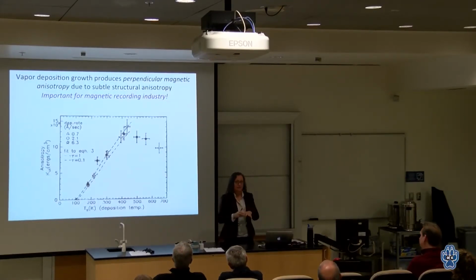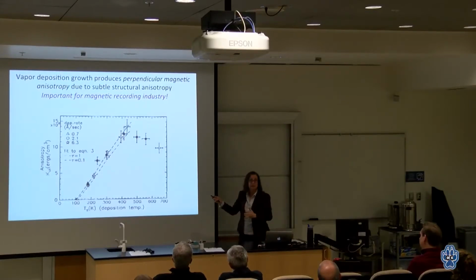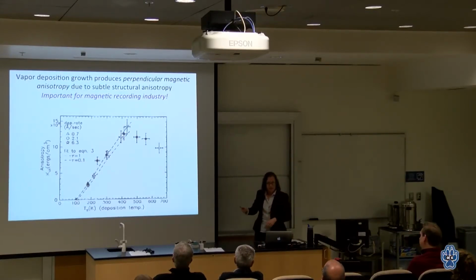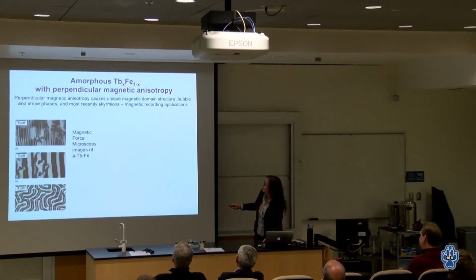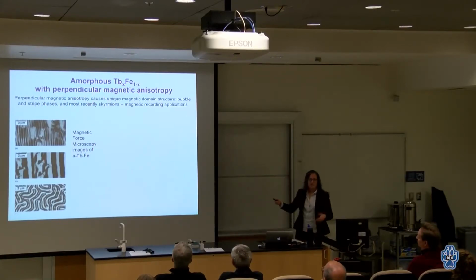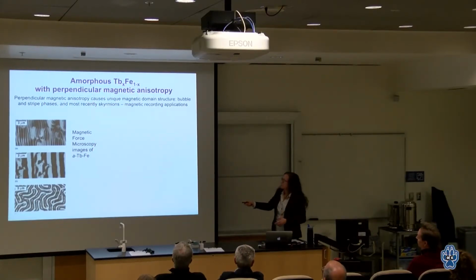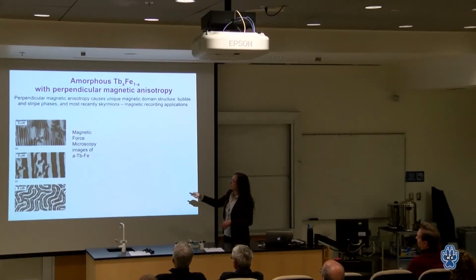Like I said from the beginning, these are big broad distributions, and you've got a tiny shift, a little more terbium iron out of plane, a little more iron iron in plane, that is enough to give you a really large effect. That effect has been useful for various versions of magnetic recording. But I want to show you in particular, this is an interesting one, it causes interesting magnetic domain structures. These are all magnetic force microscopy, basically a way of imaging magnetic domains, of amorphous terbium iron.